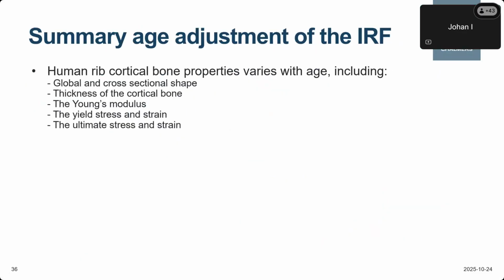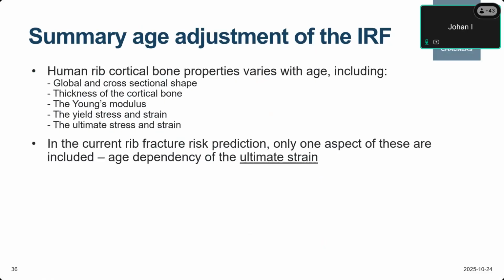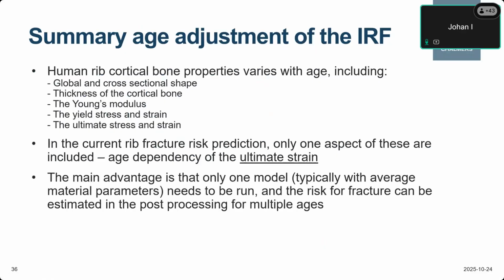If we then summarize this section on the injury risk functions: human cortical bone properties vary with age, including global and cross-sectional shape, thickness of the cortical bone, Young's modulus, yield stress and strain, and ultimate stress and strain. In the current rib fracture prediction, only one of these aspects is included, and that's the age dependency of the ultimate strain. The main advantage is that only one model, typically with average material properties, needs to be run, and the risk for fracture can be estimated in the post-processing for multiple ages.